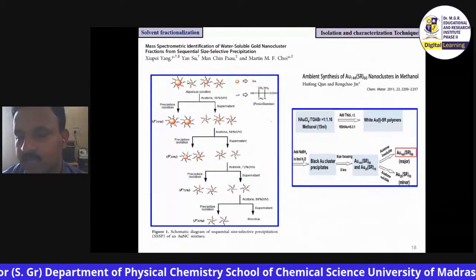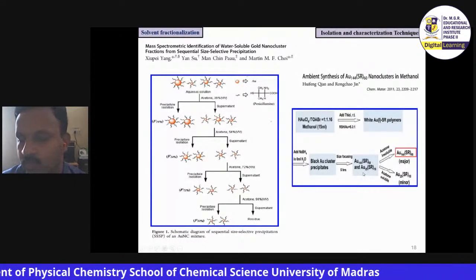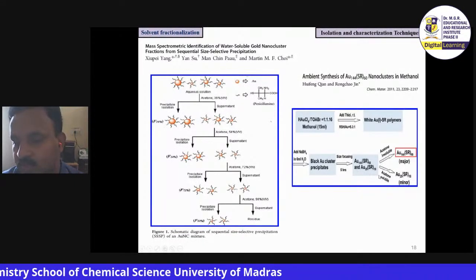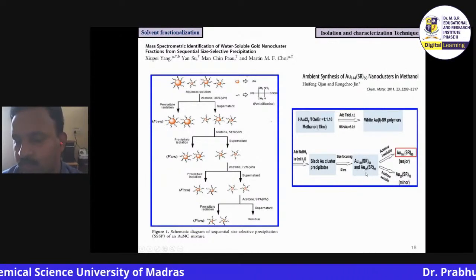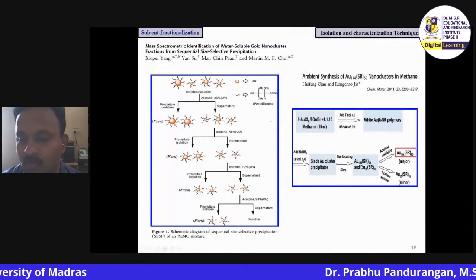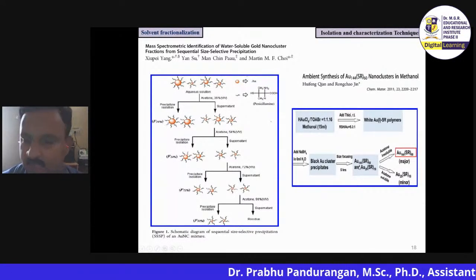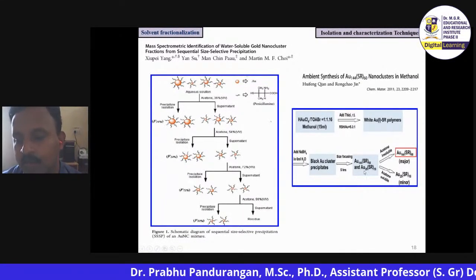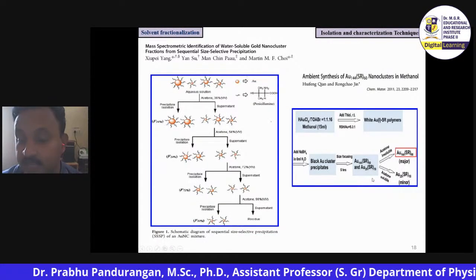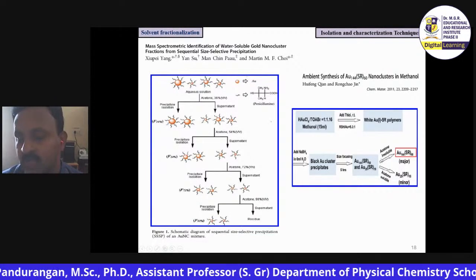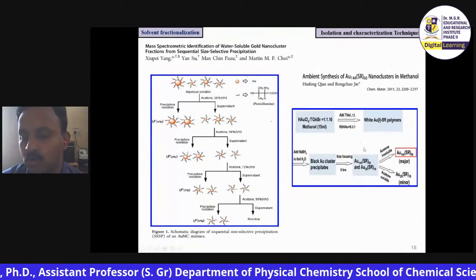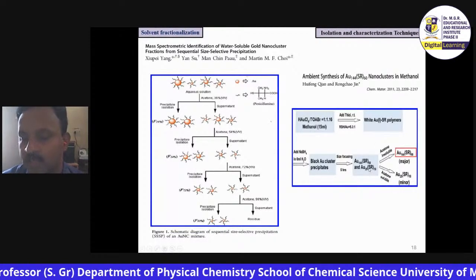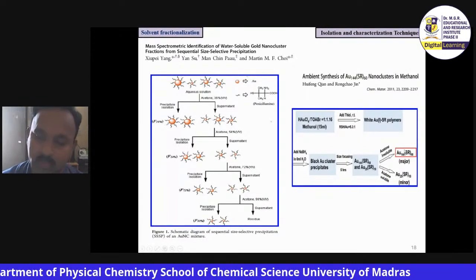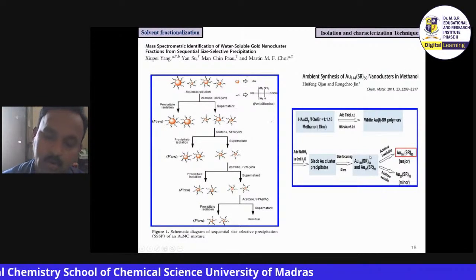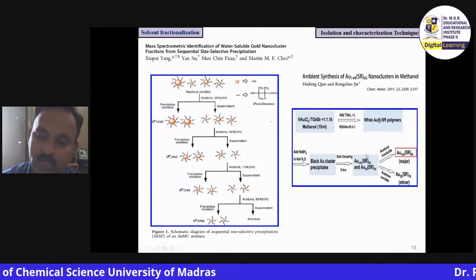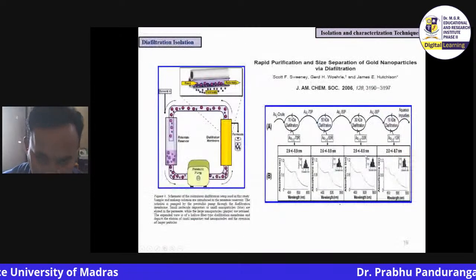So the ligands will decide what solvent I can use to do the fractionation and separate different size particles. You can see at the right extreme, I have gold 144 and gold 25. These are two different sizes. You see the beauty: gold 25 is 1.1 nanometer and 144 is close to 1.6 nanometer. We are only playing with 0.5, and it is highly monodispersed. If you use acetone in this mixture, gold 25 will be soluble in acetone, whereas the larger cluster will not be soluble in acetone. Solvent plays a vital role in separating monodispersed particles from polydispersed crude particles.